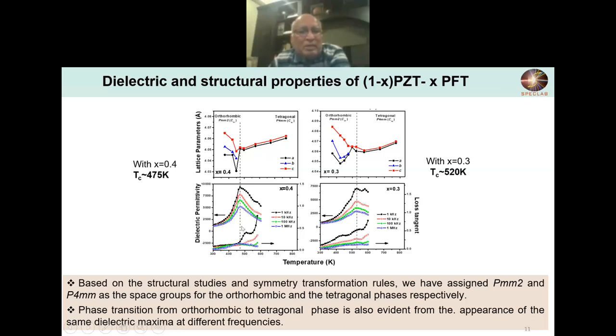Another proof comes from the dielectric measurements. We did dielectric measurements in this material as a function of temperature, and we can see the dielectric maximum occurring at the same temperature as the orthorhombic to tetragonal phase change. This is another proof that we have a structural phase transition at this particular temperature, which is 475 Kelvin for x equal to 0.4, and 520 Kelvin for x equal to 0.3. We have so much data for almost every composition, but I'm presenting just typical data, only one, for you to appreciate that there is indeed a phase transition in this material.